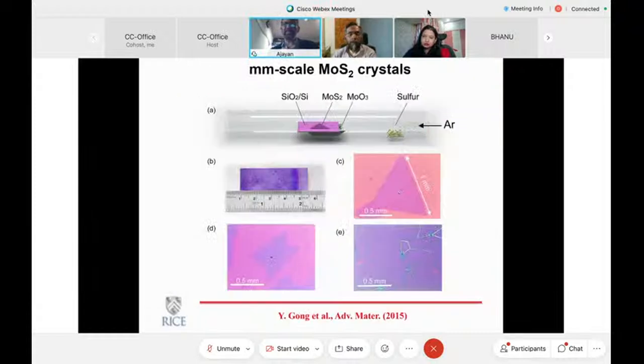There's also an attempt at the same time to grow really large single crystal-like domains. And again, we have been one of the groups that have managed to do this. So today you could actually grow almost millimeter-sized grains without these grain boundaries. I mean, defects obviously you cannot avoid, but pretty good crystals so that you can get consistently good measurements.